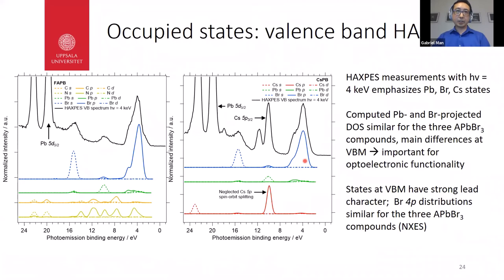So here we turn to HAXPES. On the left-hand side, the black one is a HAXPES spectrum of formamidinium lead bromide acquired at 4 keV. And on the right-hand side, this is for cesium lead bromide. At 4 keV, we don't expect to see the carbon and nitrogen states.